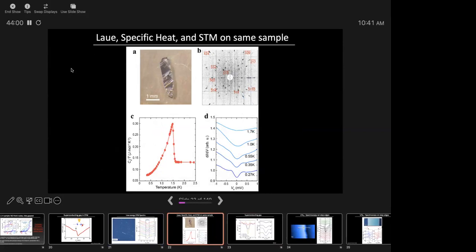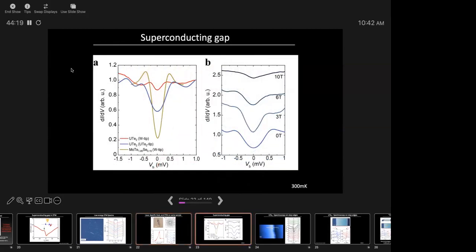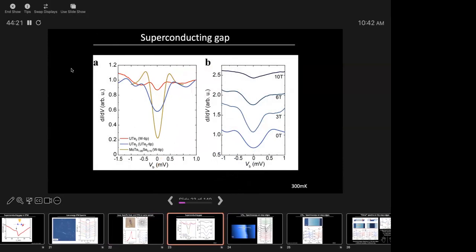Now I can show you this. Here's a sample. We did Laue to make sure it's in one phase. We looked at the specific heat of this particular sample, and then we did the temperature dependence of this gap-like feature, and it disappears close to the TC. So magnetic field dependence and temperature dependence are all consistent with this being the superconducting gap. We actually have better data now where the gap is slightly better, but really this large residual density of states continues to persist.